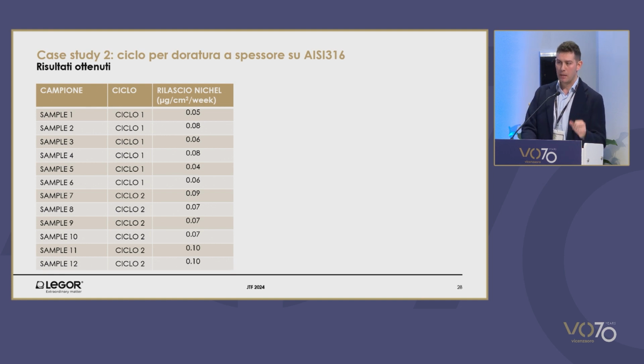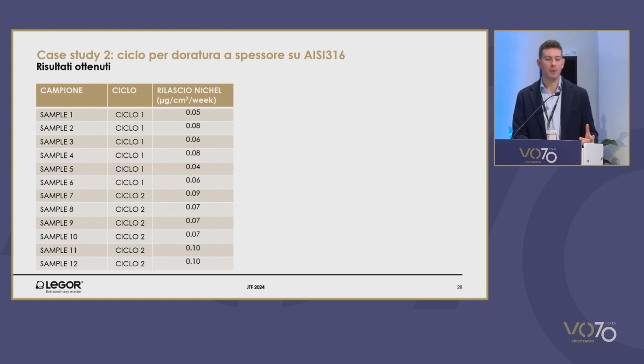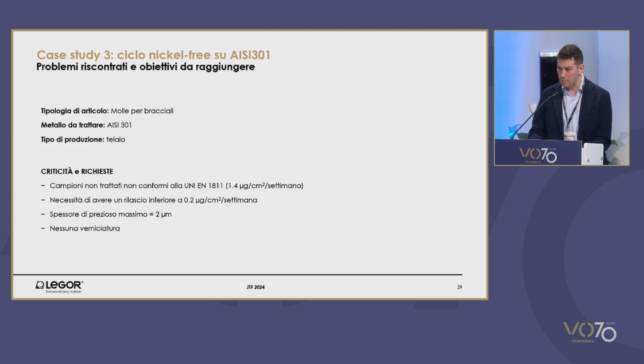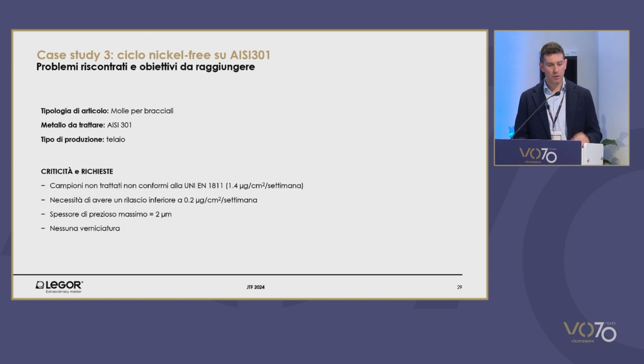Both the electrodeposition cycles were effective. Now we're using cycle 2 because it requires the least amount of 23-karat gold. In this last case study, a customer making bracelets asked us to support him in the electrodeposition of the spring with AISI 301 stainless steel. The main feature was that AISI 301 releases 1.4 micrograms, so the release was not compliant. This type of stainless steel was leading to too high a release. The client requested 0.2, despite the regulation being more tolerant.